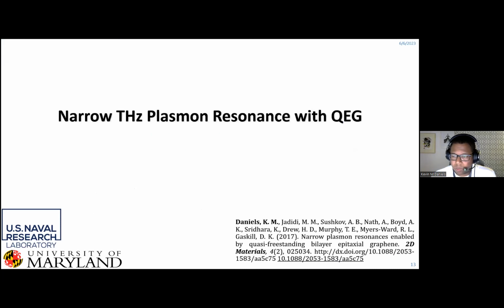Okay, so all of that to say that one of the really interesting things that we're able to show, compared to using just plain epitaxial graphene, is a narrowing of our THz plasmonic resonance using quasi-freestanding epitaxial graphene over just bare epitaxial graphene, or what people have demonstrated with CVD graphene, or even CVD graphene sandwiched between hexagonal boron nitride.